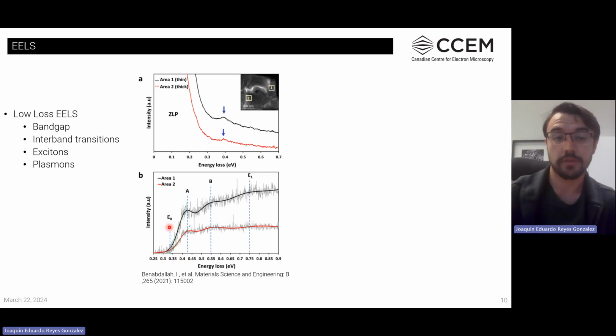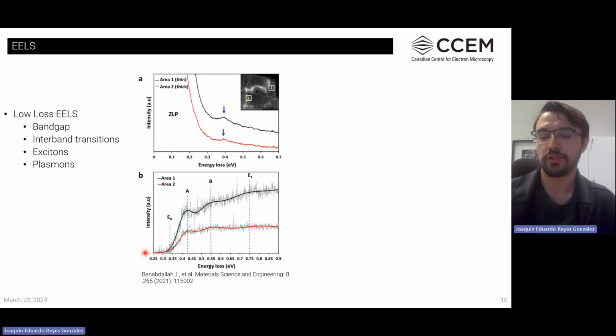For instance, we can observe the onset where we would locate the bandgap of the material. This material has a very narrow bandgap of 300 milli-electron volts, so in the mid-infrared range, which is only accessible with a high energy resolution that an instrument like Nion can provide.